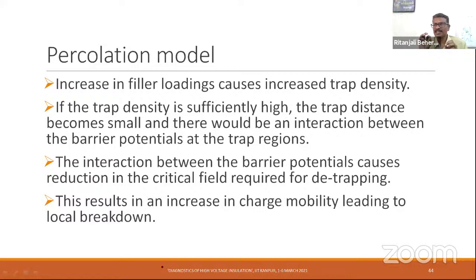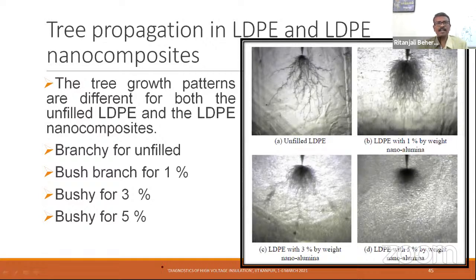that is required for detrapping. There is a critical field at which the charges which got trapped at the filler will get detrapped. If they get detrapped, they will try to move forward along the direction of the field, though slowly. So this results in an increase in the charge mobility in the polymer bulk, which leads to a local breakdown. That might be what takes place at the higher filler loading, and hence not only is the tree initiation quicker, but the breakdown also is much quicker at a higher percentage of fillers. The tree propagation in LDPE and LDPE nanocomposites is observed here.